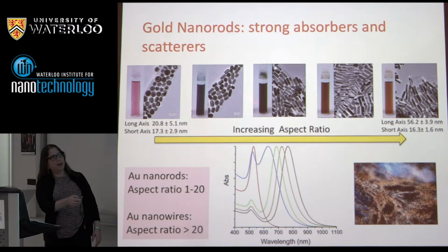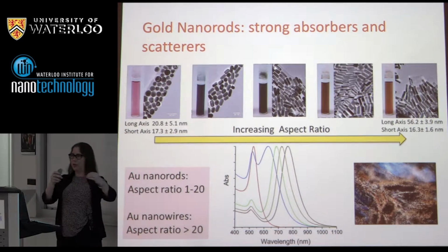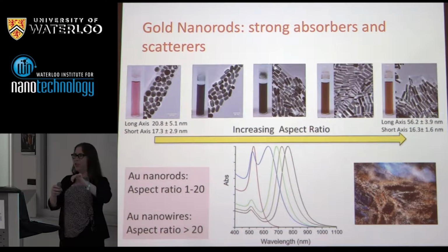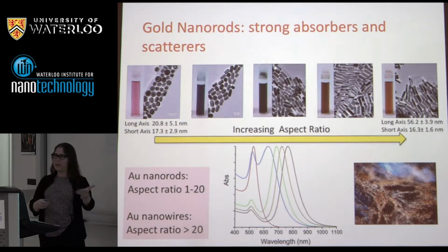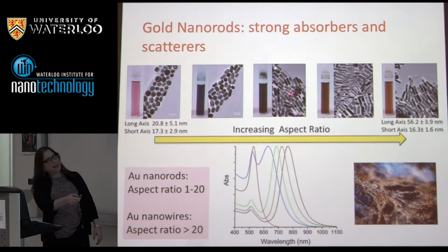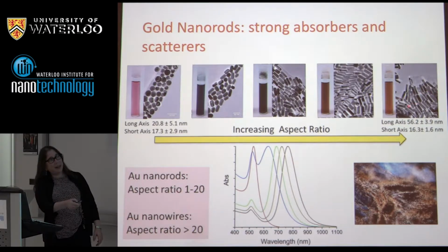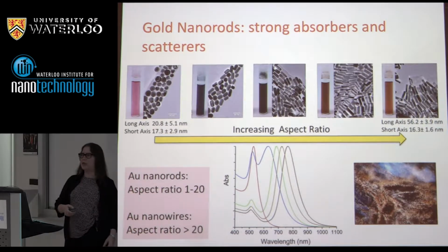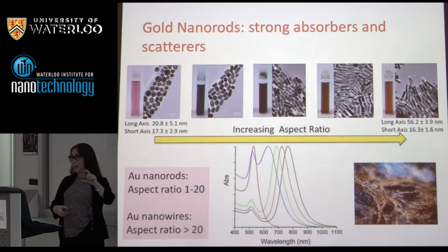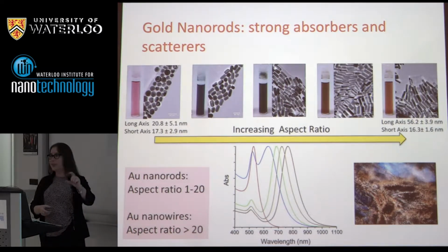And then as we go larger along the axis here, we are increasing the aspect ratio of these particles. So we're making them longer and longer in one direction, and the width isn't changing too much. So the aspect ratio here is length divided by width. So increasing the aspect ratio, it's still a pretty tight range if you want to think about it that way. And these solutions here are 1 nanomolar solutions in water of our particles. So this tells you these are strong absorbers, right, compared to a lot of molecules. Extinction coefficients 10 to the 9th per molar per centimeter on a per particle basis.